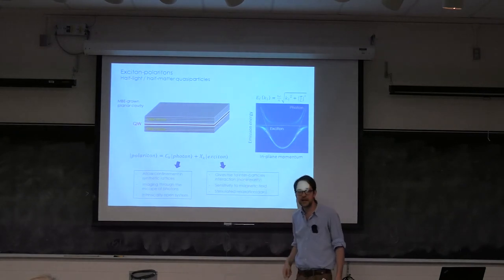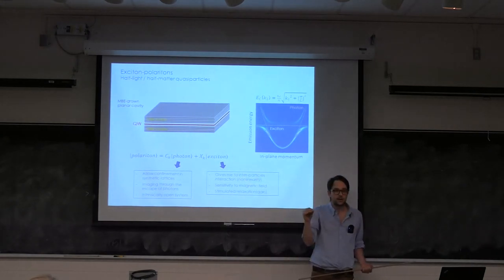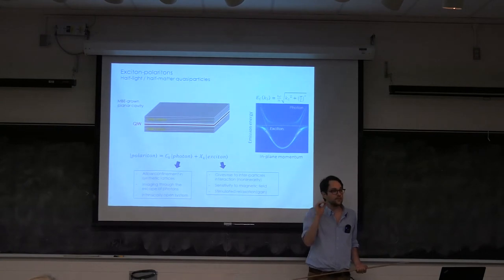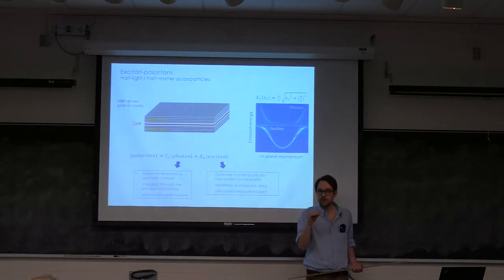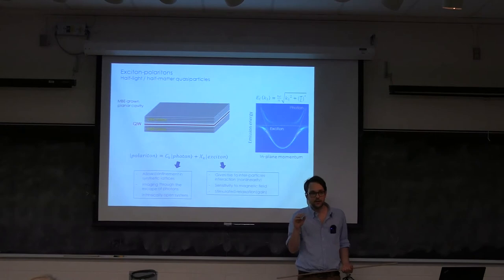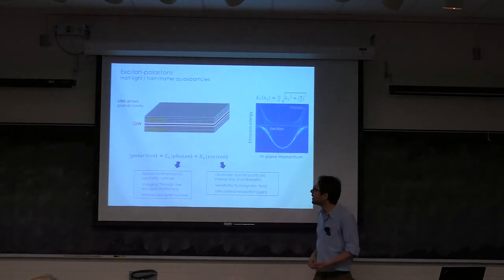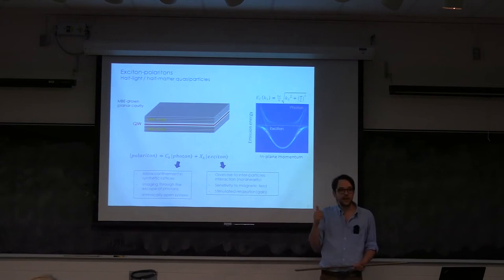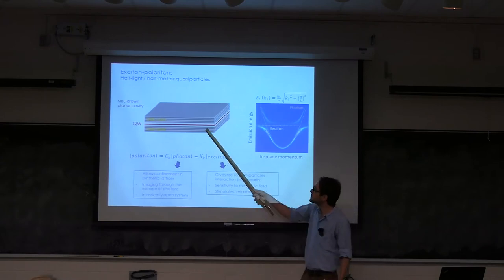And at the center of this cavity, we introduce a quantum well. And the fundamental excitation of this quantum well at cryogenic temperature at 4 Kelvin, all of these experiments I'll be showing are done at 4 Kelvin, are excitons. And these excitons have a dipole moment. And these excitons will absorb photons confined within the cavity.